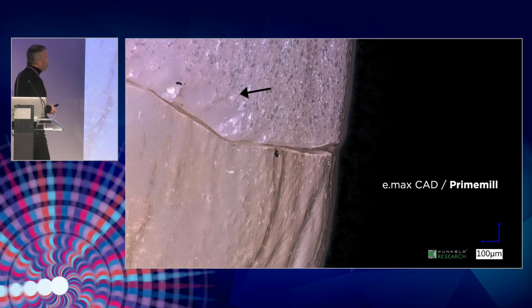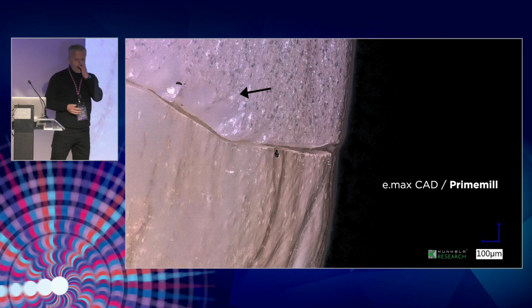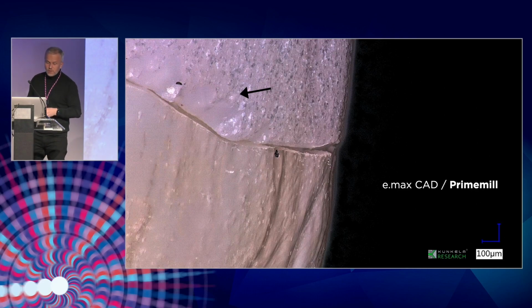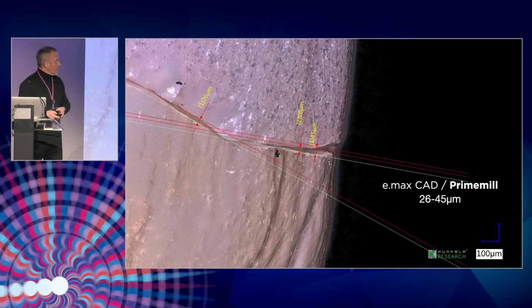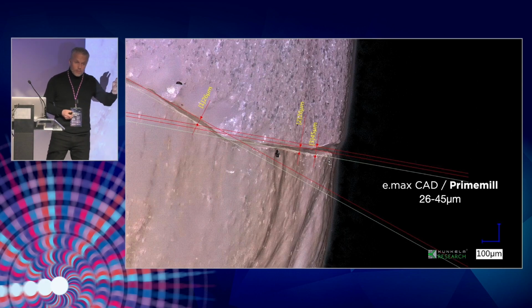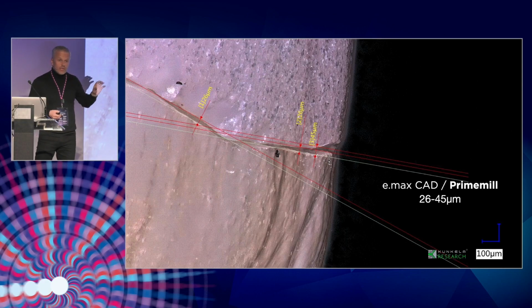Look at lithium disilicate. Lithium disilicate was the worst material which appeared in our study, because of the strongness of the material. Each sample has this chipping on the surface. It doesn't matter which milling unit we used, always we found the big chipping around the margin. The gap was acceptable, but the problem is how strong the material is, and definitely this material is the worst